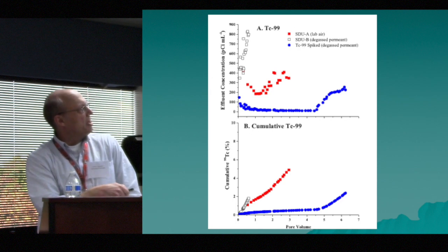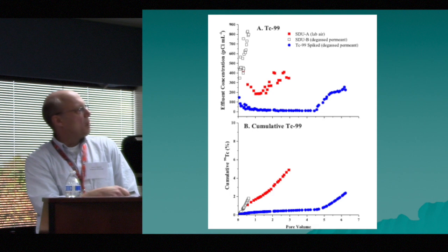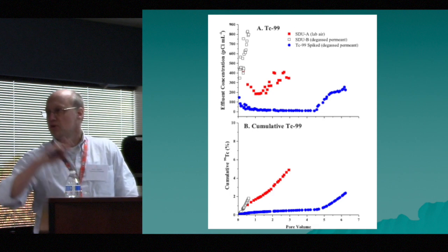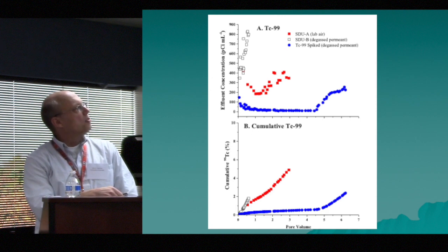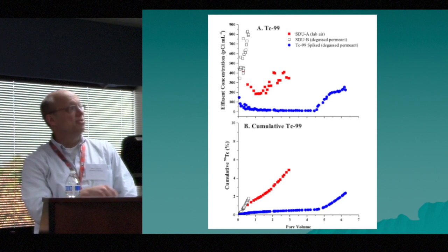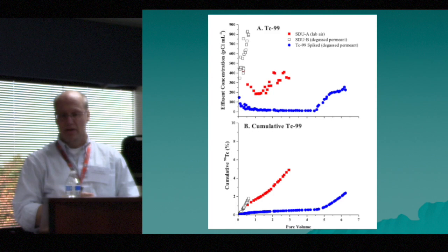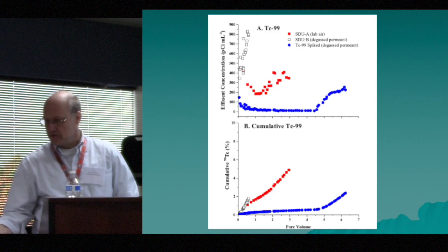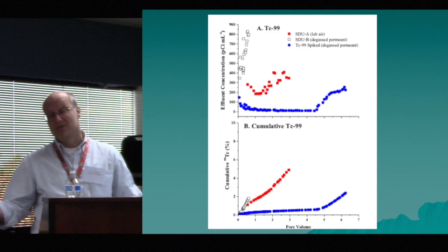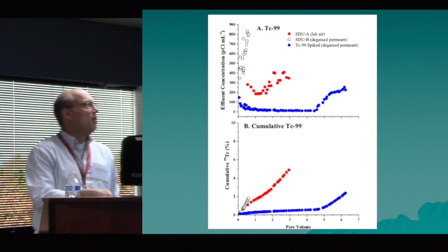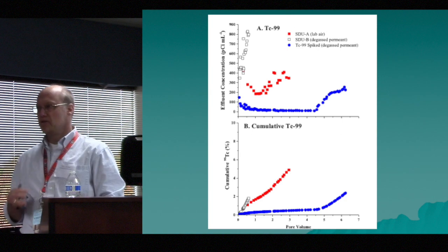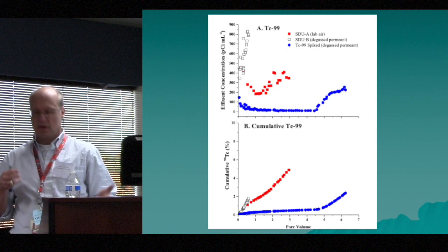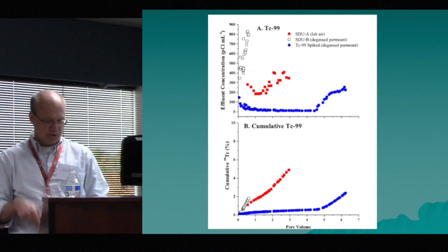This other one, the simulation, it was very low until way out here after we've gone through several pore volumes, and then all of a sudden it started to come up. And while this coincides with a decrease in the hydraulic conductivity of that sample, so it could be a residence time effect as well. But it also could be something to do with changes in the phases that are controlling solubility and controlling the way water moves through the system. Next slide.